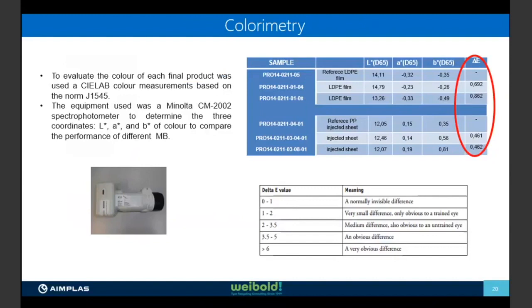If we have values between 0 and 1, it means that it's almost impossible that you can find any difference in color between any of the specimens. So the impressions that we had at first glance were confirmed by the measurements of color. So it means that we reached a good dispersion of carbon black, and we can replace different types of carbon black for coloring. Another issue will be if we can find the same performance in UV protection or in antistatic properties and so on. This is something that can be studied, but in principle, at least in color, we obtain very good performance.